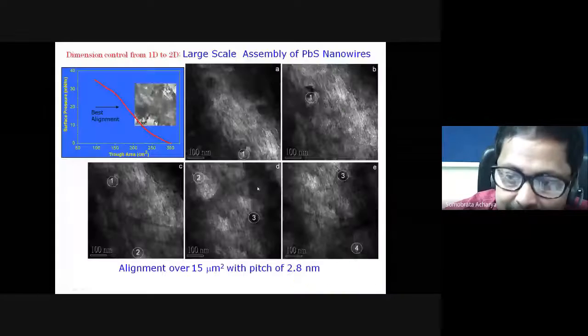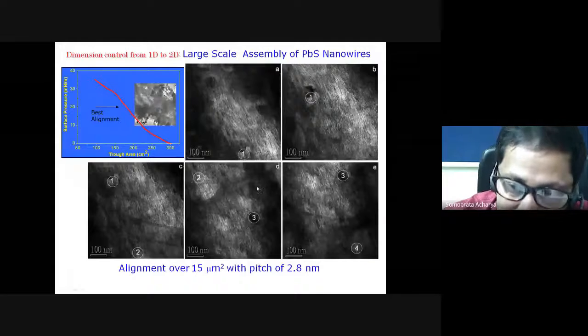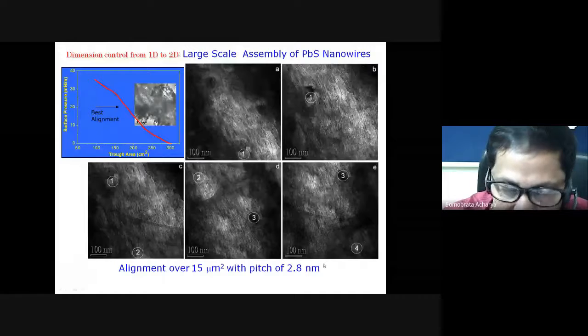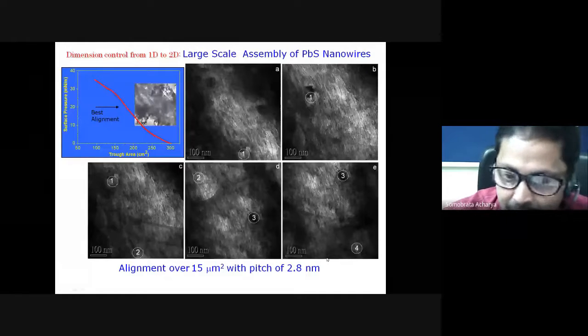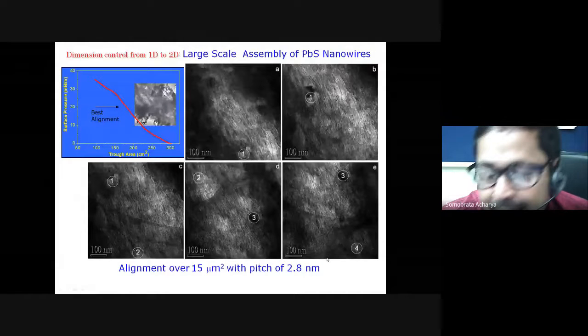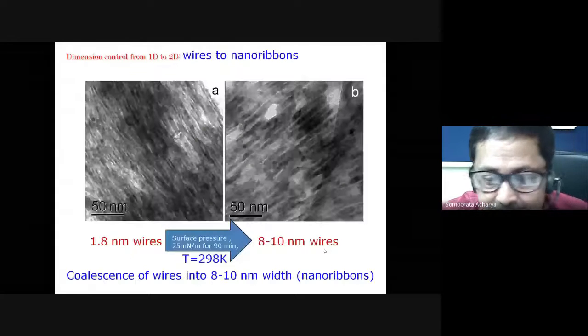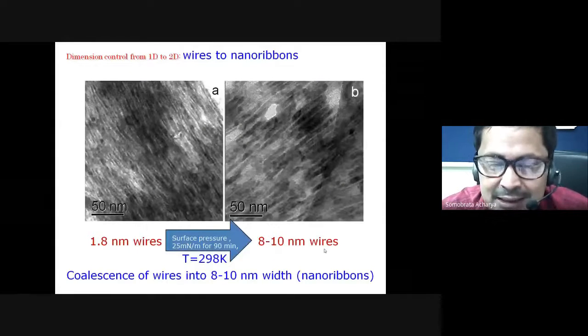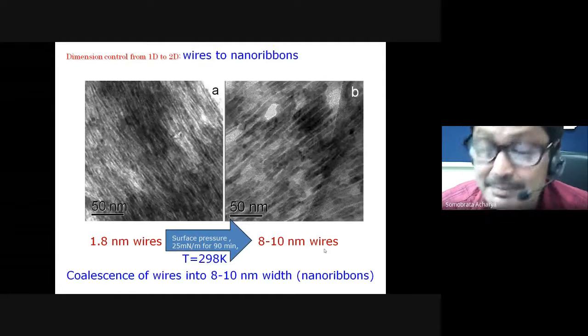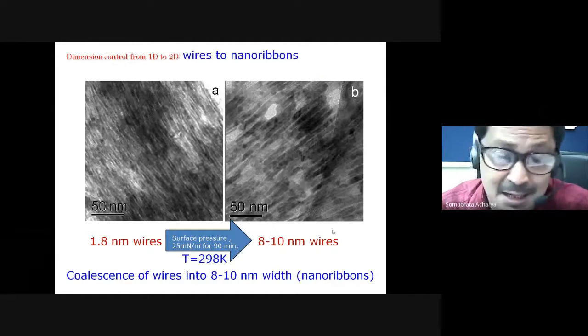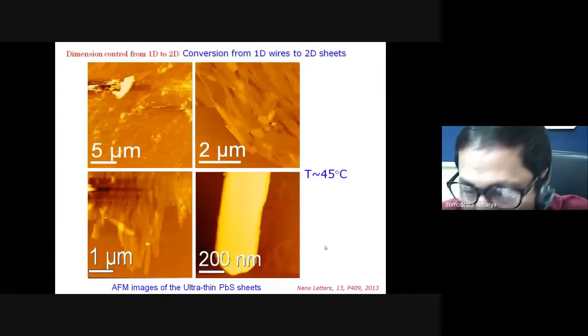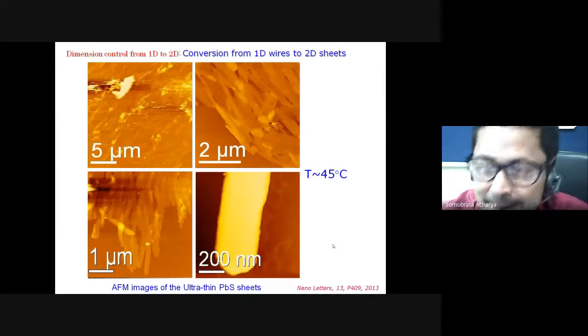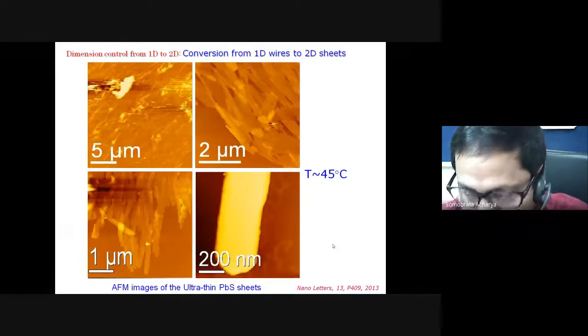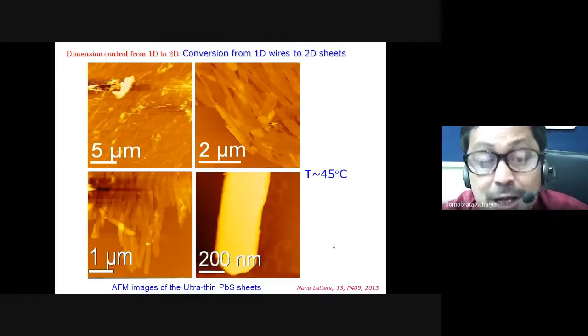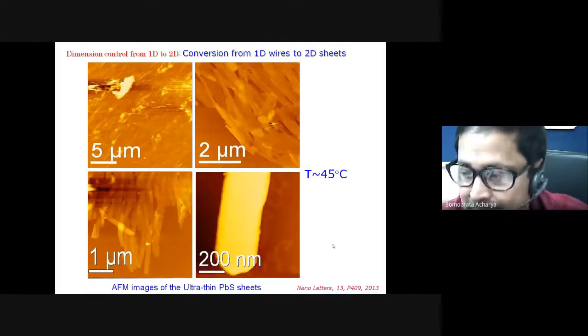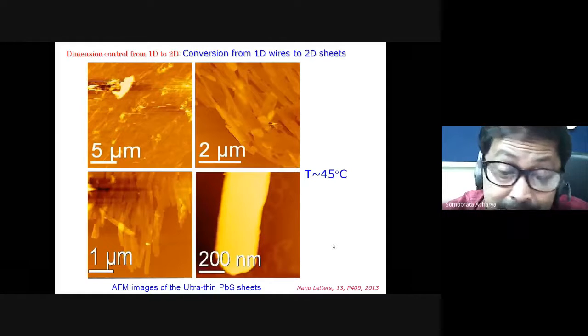Also, you can fuse these nanowires in a side-by-side manner. First, you align this nanowire along a certain direction by means of this surface pressure, and then you hold it for some time. Eventually, you can see these nanowires are merging in a side-by-side fashion, okay, side-by-side coalescence, and eventually you can obtain two-dimensional sheets. So you have started with one-dimensional conversion, and now from one-dimensional to two-dimensional conversion, and that too has been done at the air-water interface of a Langmuir trough.